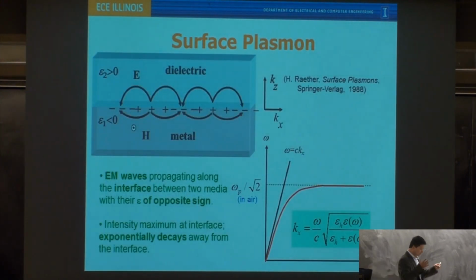So what is plasmon? Probably many of you know surface plasmon very well. Basically, that is a collective electron movement at the interface of dielectric material and the metal materials. So you would expect you have free electrons in metal, because they're conductors, and they will move in a periodic way along the interface between a dielectric and metals upon the excitation of external electromagnetic waves. But we also know this very famous dispersion relationship, that there's no way you can directly couple your free space propagating electromagnetic wave onto surface plasmon, because their dispersion curve does not have an intersection point. That's why people use either a prism or high refractive index material as an intermediate coupling material, or use nanostructure grating to couple the free space EM wave onto surface plasmon.